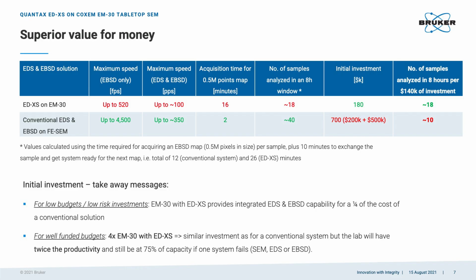Here you can see a table where we have different factors to consider, and we compare the numbers of the ED-XS, Quantax ED-XS on EM30, the Coxem tabletop, and most of the numbers refer to the EBSD detectors. And then compare with a conventional EDS and EBSD system, which usually goes on a field emission SEM. So if you compare the maximum speed, for example, for EBSD, that would be 520 for eFlash-XS, and up to 4,500 frames per second for a latest generation CMOS fast EBSD detector.